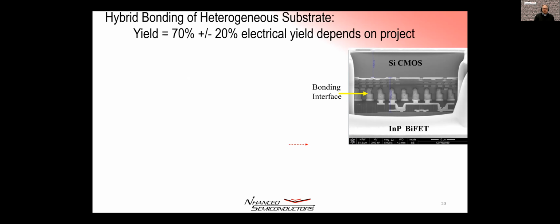We do gallium arsenide, silicon carbide, lithium niobate, gallium antimonide, gallium nitride, all in various combinations and with CMOS. So you can get very, very high figures of merit. If you're familiar with Johnson figures of merit, we can easily get 3 orders of magnitude performance improvement as opposed to any silicon process or any other single process. Heterogeneous integration gives you a lot of performance boost.